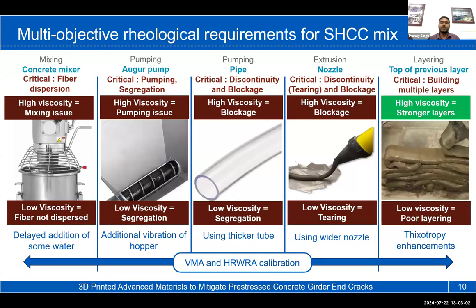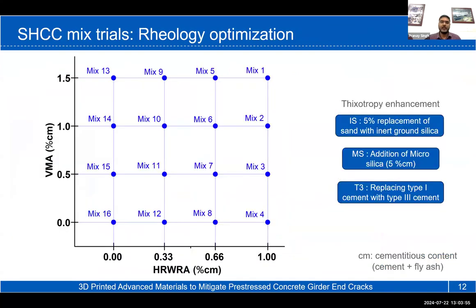The rheological requirements were established through a series of experimental investigations, and we observed that strain hardening cementitious composites have different rheological requirements which are contrasting from each other for each stage of the processing. So we start with the mixing, and at that stage, fiber dispersion is crucial for achieving the strain hardening behavior. And then at pumping through our extruder and through the tube, there is a different rheological requirement. And later on, for extrusion and buildability, we have some different viscosity and rheological requirements. We achieved it by calibrating two ingredients, VMA and HRWRA, and later adding some more ingredients that I will discuss in upcoming slides.